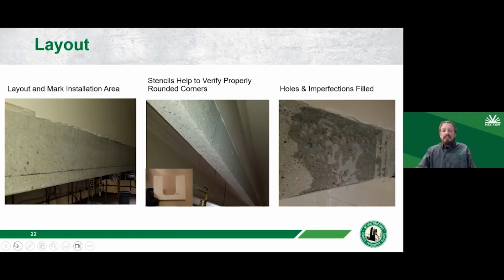Once we've got those kind of variables figured out, we get into the layout of the FRP product. So as you saw in the past in the design, we wanted to put FRP on a beam. This beam is coated. We want bare concrete. We can't install FRP over any sort of coating, paint, anything else that's there. So grind the existing coating off, open up the pores of the concrete. We want that epoxy resin. We want the ability of that resin to adhere as best we can to that parent concrete, and then we make sure that it's all cleaned up and ready to go.